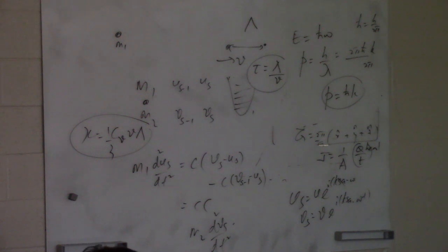But is that real? It never goes to infinity because the phonons always get scattered from the surface boundary. Ideally it is infinite, but phonons get scattered from the finite sample boundary, so this becomes a finite value. Then what is the total? The kappa goes like T cubed.